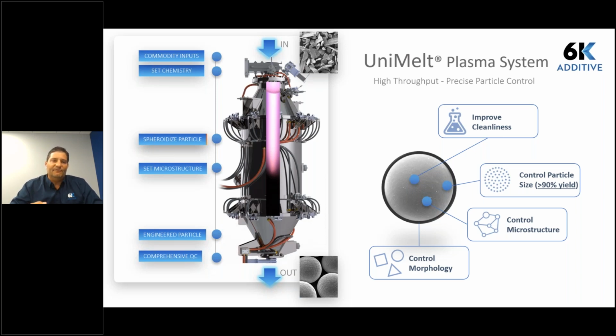So we're simply doing the step that facilitates a morphology of powder that allows these things to be used in additive manufacturing. Now, there are some benefits that come along with that, in that we can improve cleanliness, particularly interstitials for things like gases. But the key thing is that we can take a lot of different types of materials and input it through the plasma and melt each of those individual particles and allow them to become spherical and give us the properties that are important to most of the additive manufacturing machines when it comes to the utilization of powder. So we call it a volume in, volume out process.